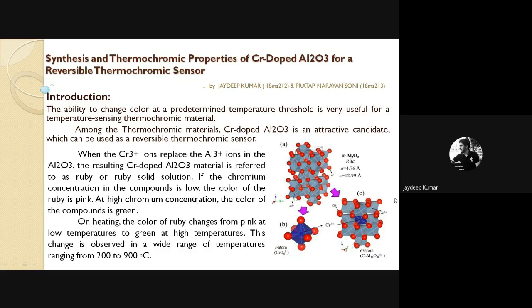But at high temperature, what happens? The chemical bonds of this octahedral cage of oxide ions expand, and the chromium ions become more relaxed, due to which it gives its characteristic green color. And this competition between these two cations to be in a properly sized octahedral cage of oxides is thus the origin of the thermochromism.